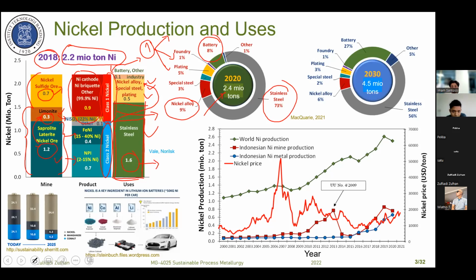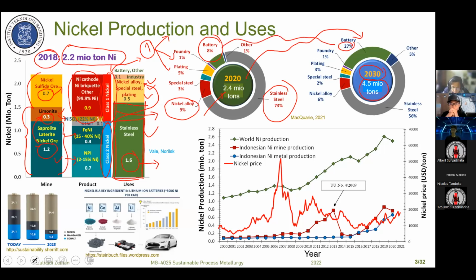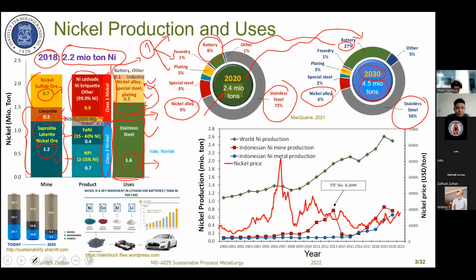But we know that in the future more nickel will be used for battery, for EV, for electric vehicles. So if we see the prediction for 2030, around 4.5 million tons of nickel will be produced worldwide. And the proportion of nickel for battery increases from 8% to 27%. The majority of the nickel, if you see from this data, is still stainless steel. Yeah, so number one is stainless steel, and number two is battery. And the third is usually nickel-based alloy, which is used for other purposes, for example, for jet turbine, etc.